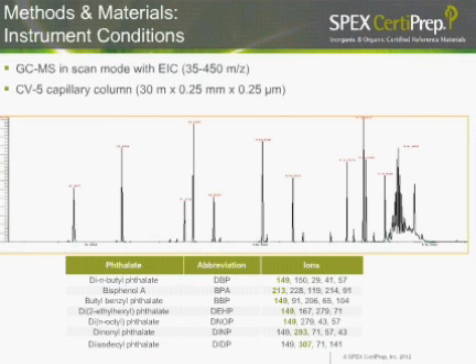What we used was a GCMS in scan mode, and we used a CV5 capillary column of just standard dimensions. We monitored for the 6 restricted phthalates as well as Bisphenol A. We did primarily quantitate on the 149 ion for most of the phthalates. We did look at 213 for Bisphenol A. One of the exceptions is the coelution of the two larger phthalates at the end, the diisodecyl and the dinonyl phthalate. For those phthalates, we did monitor alternate ions.